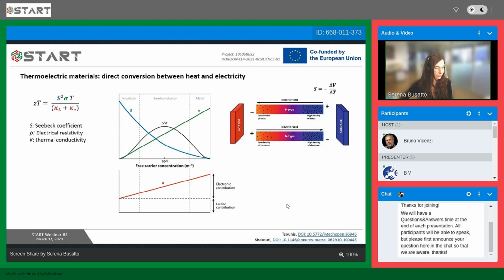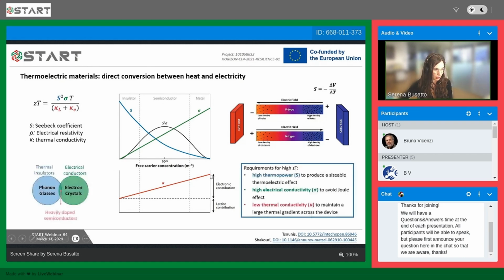This is why the requirements for having high ZT are to have a high thermopower to produce a sizable thermoelectric effect, but also to have a high conductivity to avoid Joule effect, and also to lower the thermal conductivity, as you can see from the formula here, to maintain a large thermal gradient across the device. So basically what we need to find are the so-called phonon glasses electron crystals, so thermal insulators but electrical conductors, which in fact are found in heavily doped semiconductors.